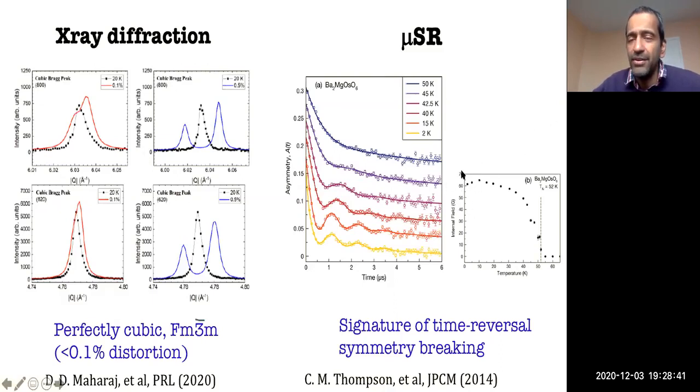The kind of fields that you're getting here already tell you that there is something odd about it. So either it has to be close to some critical point, some kind of quantum phase transition where you're going from some non-magnetic state into a state that has very weak magnetic order, or it has nothing to do with the electronic dipole moment at all, and it's something completely different. Somehow I don't think it was quite clearly recognized in this older work that this is an unusually weak field, and that this is an important question.